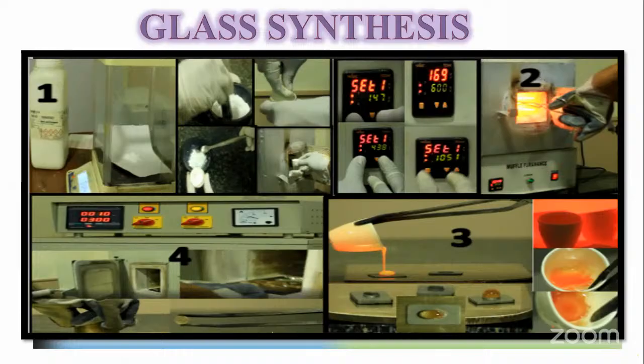temperature. Between 410 and 450 degrees Celsius, if I'm able to set it, I would be expelling chlorides, halides particularly. And if I set it at 600, it need not be precisely 600. It could be from 600 to 650, depending on the batch that you prepare. So if you set it at that temperature, you are trying to expel the carbonates that are being used from your precursor.